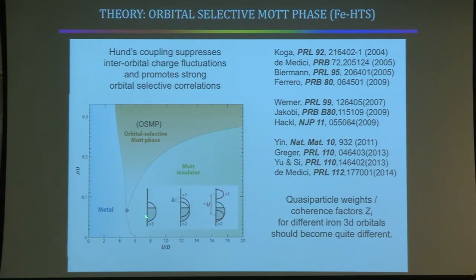If there are 2 orbitals, it's formally possible, and it's found in these calculations, that you can end up in a situation where 1 orbital undergoes a Mott transition and is split by on-site interactions, while the other orbital is not, leaving it in a metallic state. That's an orbital selective Mott phase, as defined in all these papers.